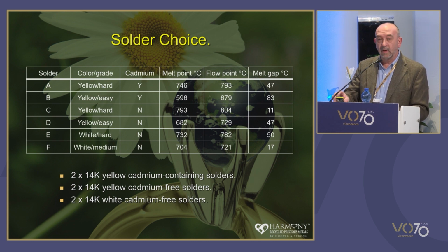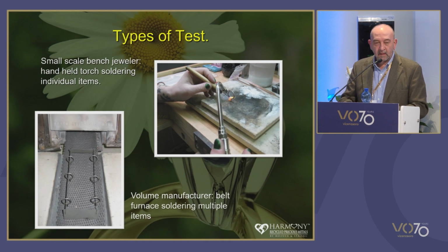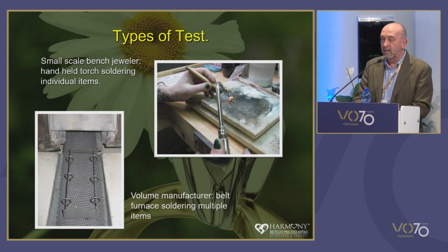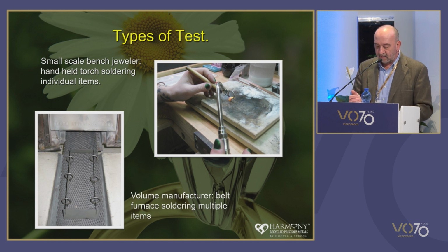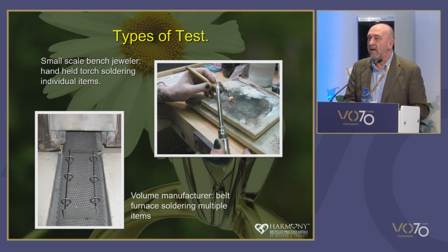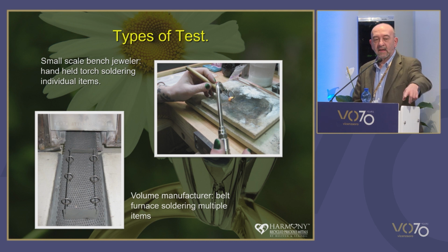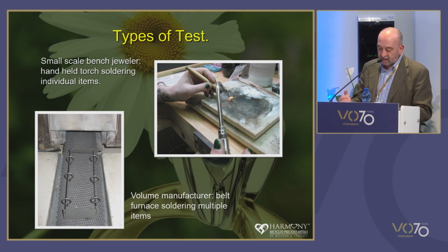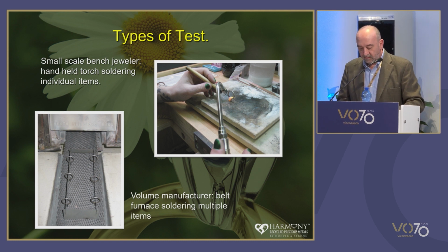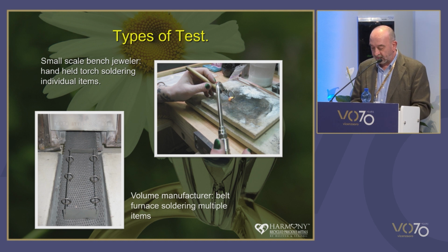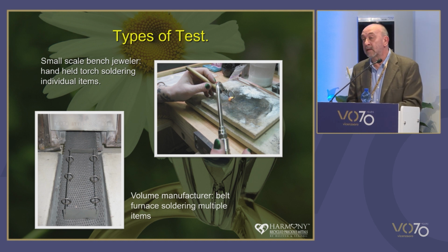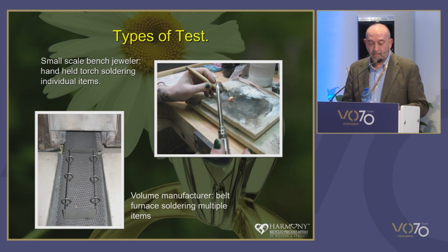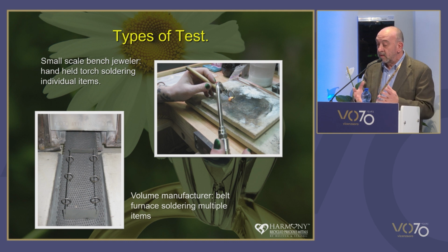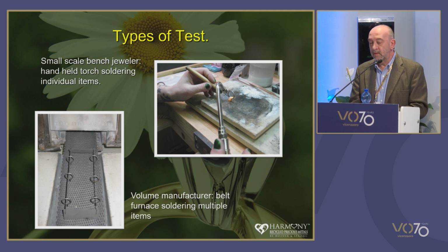So the type of test we're going to look at, we came up with. On the small scale, a bench jeweller usually works on individual items, one at a time, using a handheld torch, so an open flame, as the heat source. A volume manufacturer is going to assemble multiple items at the same time using jigs, usually in an atmosphere-controlled belt furnace. You can see a little example of those in the picture there. So for this study, each test is going to be processed in these 2 ways. For torch soldering, boric acid was used as a flux to protect the workpiece, and in the belt furnace, cracked ammonia was used as the protective atmosphere. And we hoped this approach would highlight any differences in solder performance between the 2 methods.